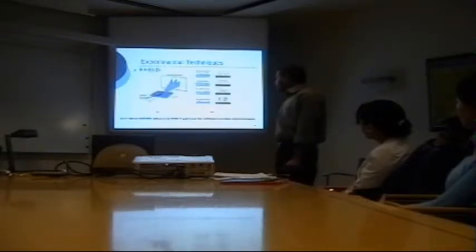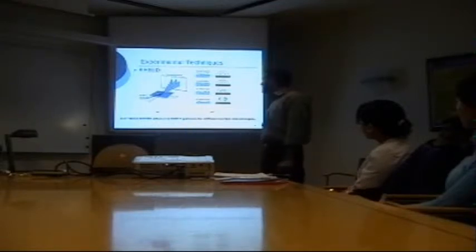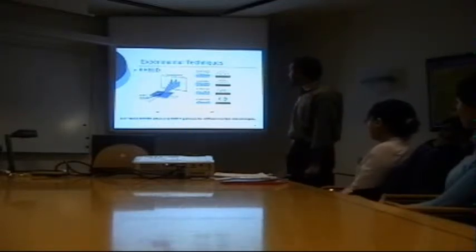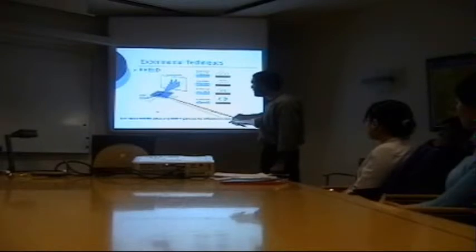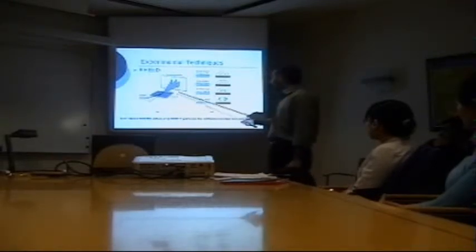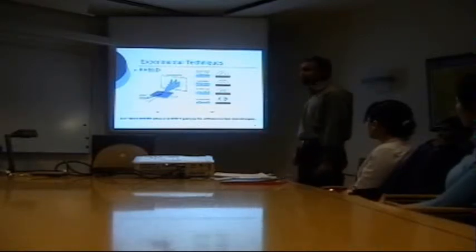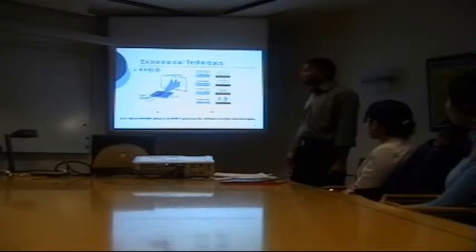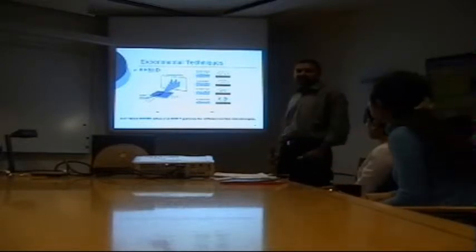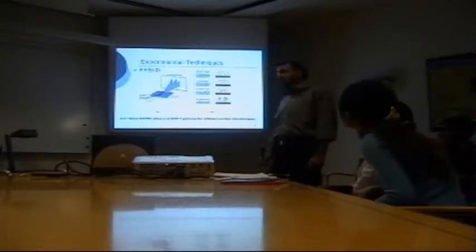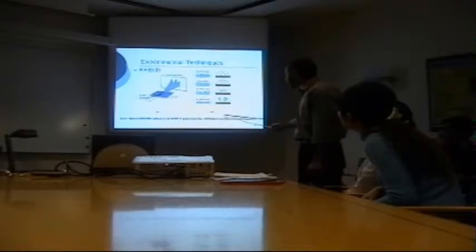Here in figure A, you can see a typical RHEED setup. In RHEED, an electron beam hits the surface, and after hitting it, it is diffracted. This diffracted beam hits the fluorescent screen and produces the pattern called the RHEED pattern. There would be different kinds of RHEED patterns for different surface morphologies, as you can see in figure B.